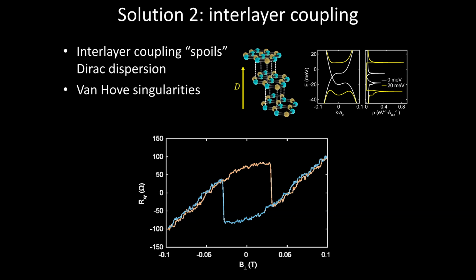So if you add a couple of layers in a rhombohedral structure, for example, which is a pretty common allotrope of graphene, you find that the band structure is no longer just Dirac cones. This is energy versus momentum, but actually it has this sort of complicated structure, and it has these Van Hove singularities. These are points in the band structure where the density of states diverges. Okay, and when it becomes very large, if you tune your chemical potential through these, so you try to occupy these states where you have many states to choose from, they will generically become magnetic.